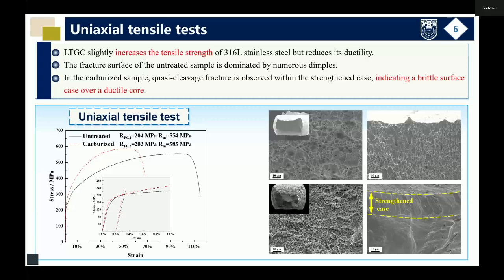We performed uniaxial tensile tests to evaluate the effect of low temperature gaseous carburizing on the mechanical properties of 316L stainless steel. The result shows that LTGC slightly increases the tensile strength of 316L stainless steel, but reduces its ductility. The fracture surface of the untreated sample is dominated by numerous dimples, which is typical of ductile fracture. For the carburized sample, cleavage fracture is observed within the hardened case, indicating a brittle surface case over a ductile core.